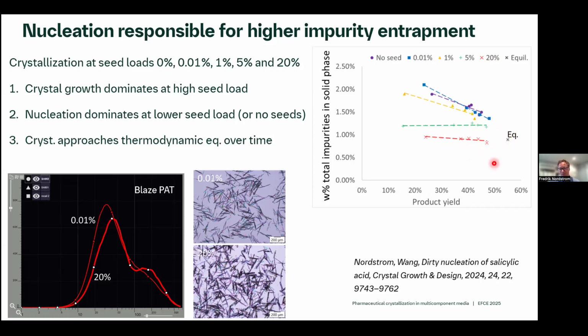So when we do these experiments, we see two things, right? If we have a high seed load, we're going to have growth-dominated crystallization. You can also see that in the Blaze PAT data here, we're getting much thicker crystals, more growth, right? And then it proceeds very close to equilibrium. So we're just getting growth there all the way down to equilibrium. But as we let it crystallize mostly through nucleation, then it approaches from the top. So what we see here is that it's the nucleation that drives the impurity entrapment early on. We have a much higher impurity level in the beginning, and then it slowly approaches equilibrium. And this change towards equilibrium takes time. It depends on the compound. For salicylic acid, it's fairly fast, but for other compounds, it's really slow.